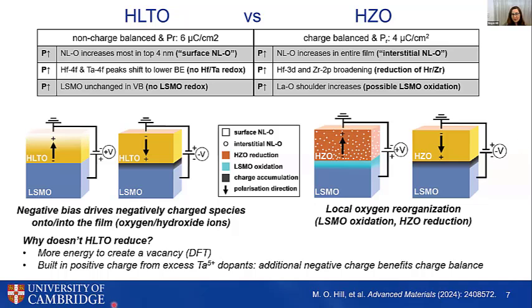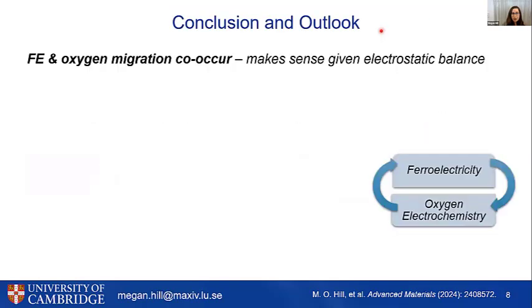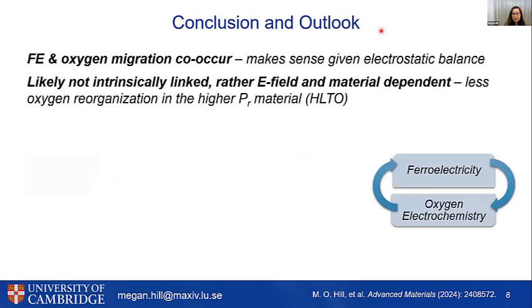But ultimately, what's important here is that we're seeing a significant reorganization of oxygen in the material that actually has a lower remnant polarization. So what this suggests to us is that, yes, ferroelectric switching and oxygen migration co-occur. This makes sense given the need to balance electrostatics, and it's been observed before. But this doesn't necessarily mean that they're intrinsically linked, because we see less oxygen reorganization in the material with a higher remnant polarization, being HLTO. And so instead, we think this is just an effective electric field and material dependent, not dependent on the oxygen reorganization.